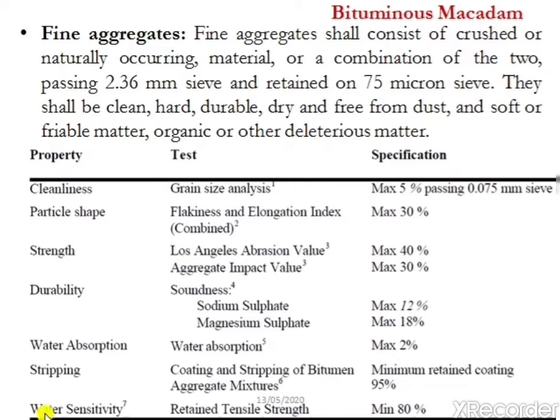The next test is water sensitivity. To determine the water sensitivity of the material, the test conducted is retained tensile strength. Here the water sensitivity of the aggregates should have a minimum of 80%. This is also called the tensile strength ratio, or TSR. The tensile strength ratio of bituminous mixtures indicates their resistance to moisture susceptibility and is a measure of water sensitivity. Moisture damage in bitumen mixes refers to loss of serviceability due to the presence of moisture. Hence, the minimum value for water sensitivity is 80%.